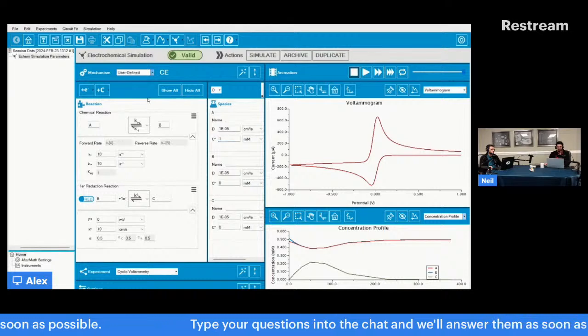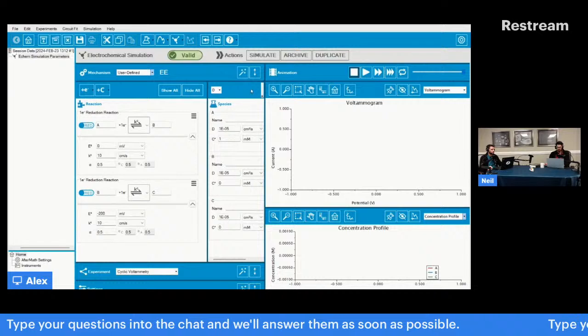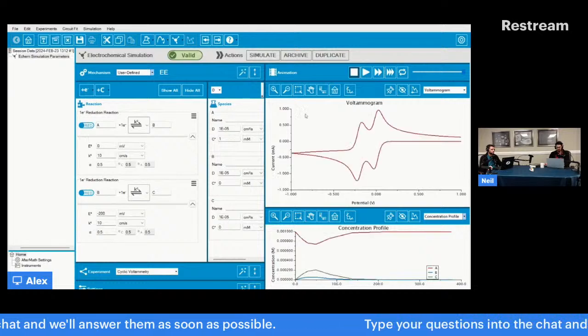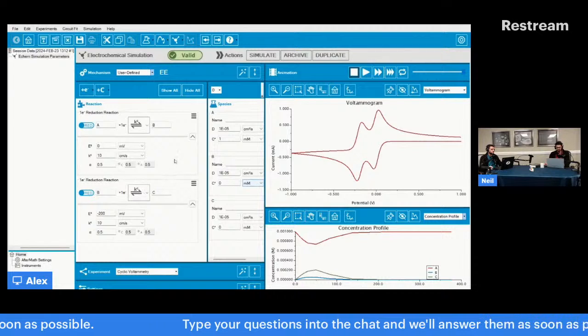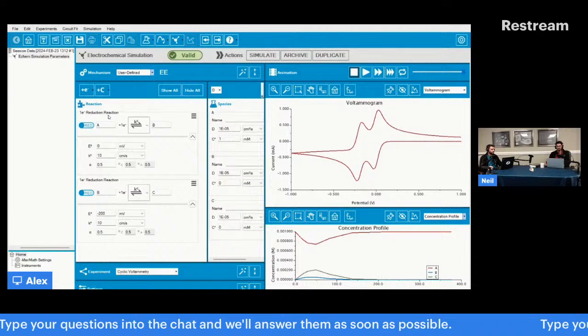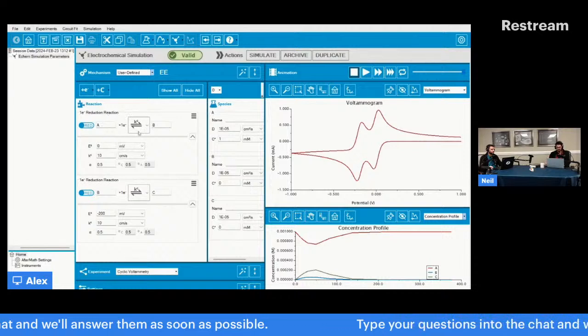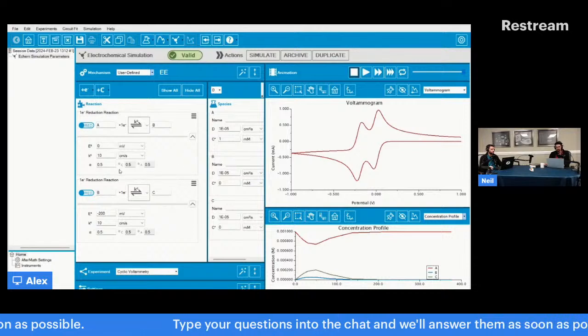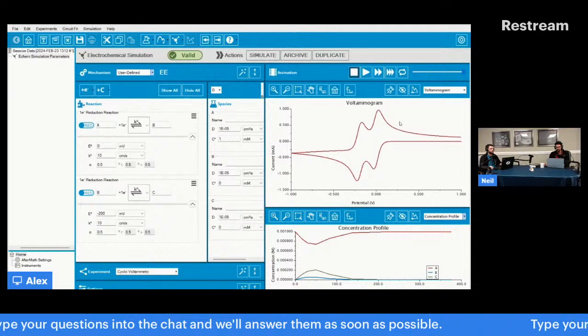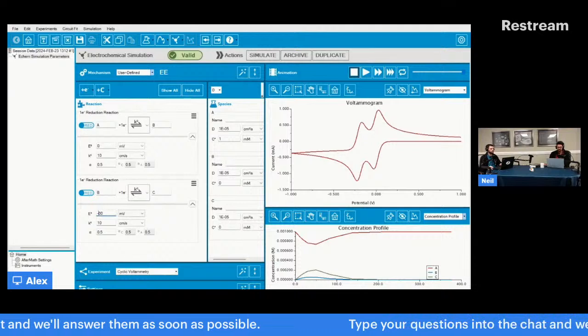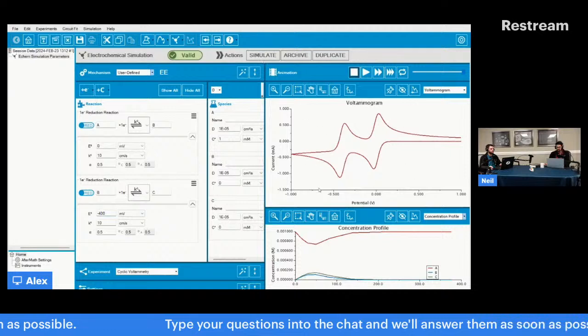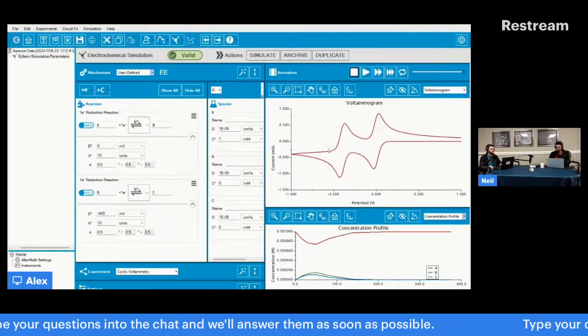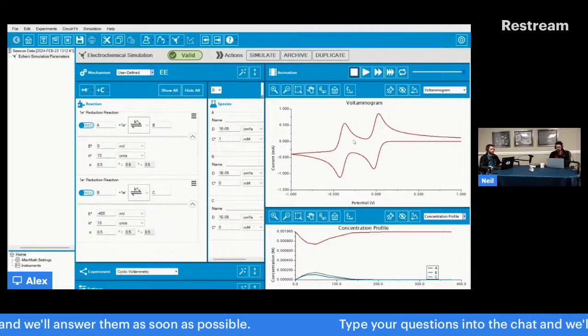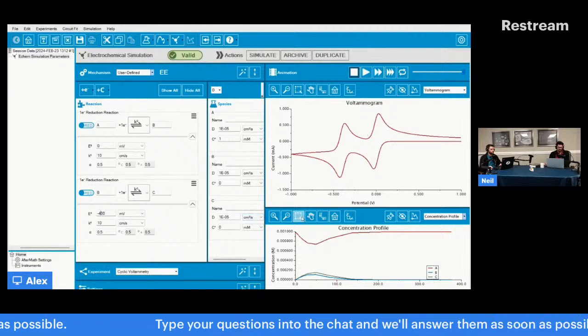to model your system to determine whether you have an EC or a CE reaction. And lastly, I'll go to a double electron transfer. Most of the time, two electron transfers will occur one after another. It's rarely the case that you'll have a sequential electron transfer where two electrons actually occur one on top of another. It'll usually be one, and then some time will pass. Maybe this is something like 400 or something. There'll actually be a bigger peak separation between one redox pair and another redox pair. It's rare that both of them will be in just one big voltammogram. So that's how I would observe a two electron versus EC and the CE type of mechanism.